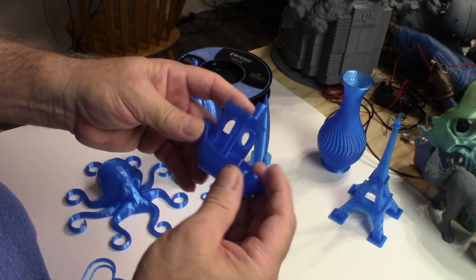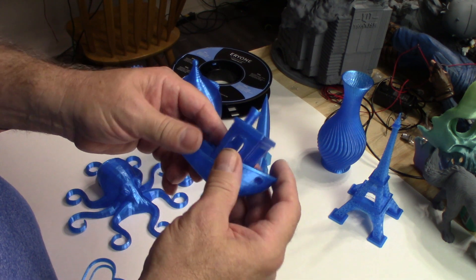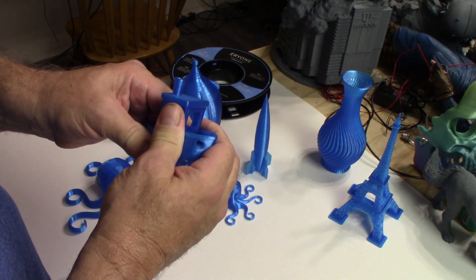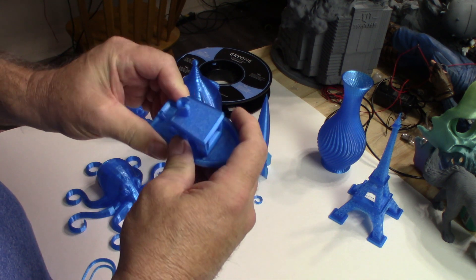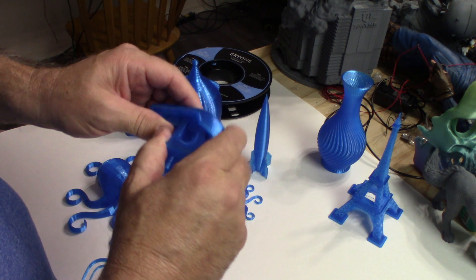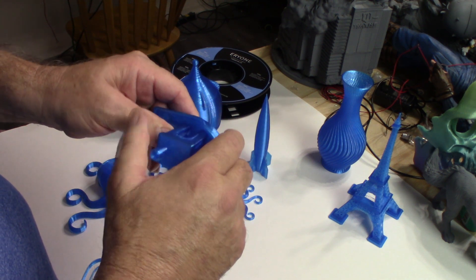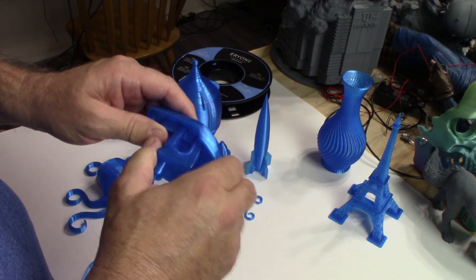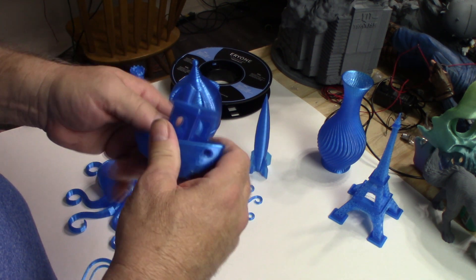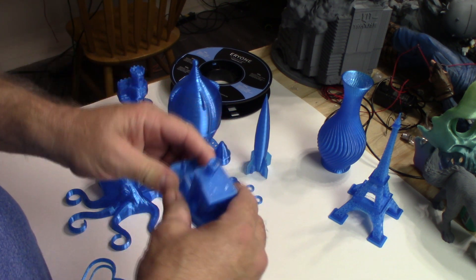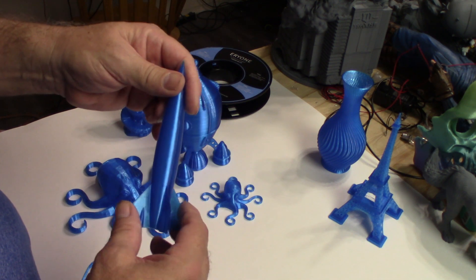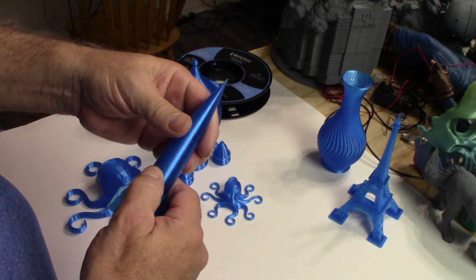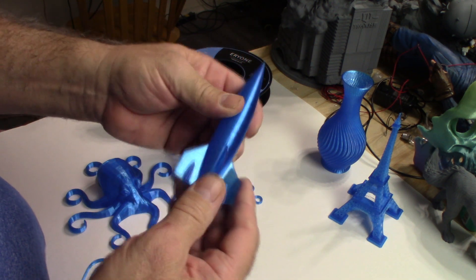I had almost no stringing on anything and I've heard that TPU loves to absorb moisture quite a bit, a lot faster than PLA might. So I suggest if you live in a humid climate and even if you don't, if you're not going to be using all of it right away, store it in a Ziploc bag with desiccant packs to absorb all the moisture. If you should get tons and tons of stringing, you're going to want to dry out your filament, whether that be via a filament dryer or oven. You'll need to dry out your filament if you have tons of stringing because it absorbs too much moisture.